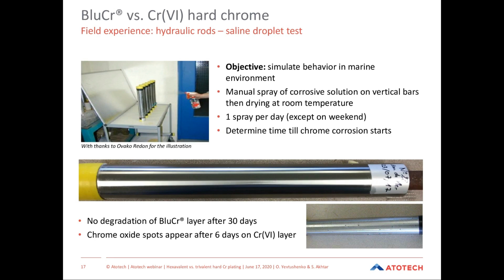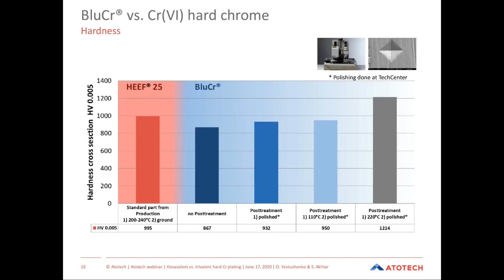Then it is dried at room temperature, and this procedure is repeated every day, and the parts are examined every day, and at the end, the goal is to determine the time until corrosion of the chromium starts. You can see here two bars, and on one you don't see any degradation of the chromium layer itself. This is the part deposited from blue chromium. You can also see the part deposited from the hexavalent bath has some chromium oxide spots, which appeared already after 6 days of test.